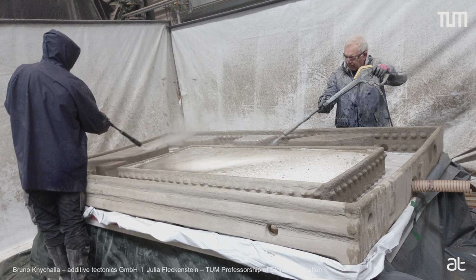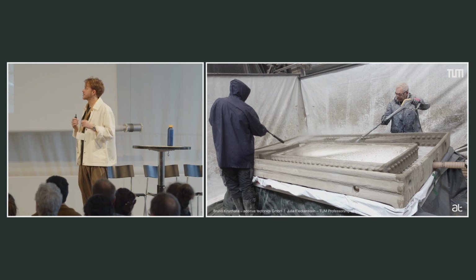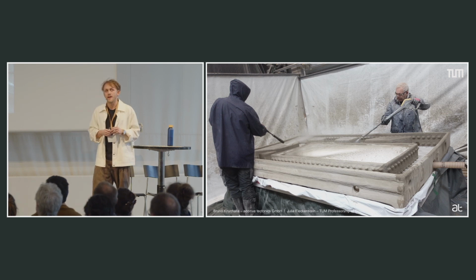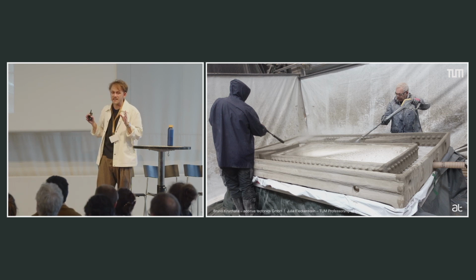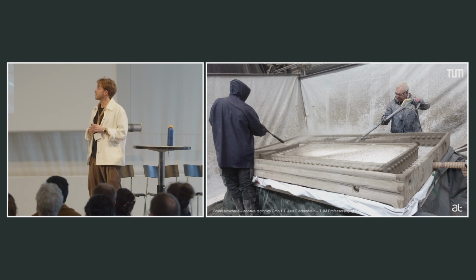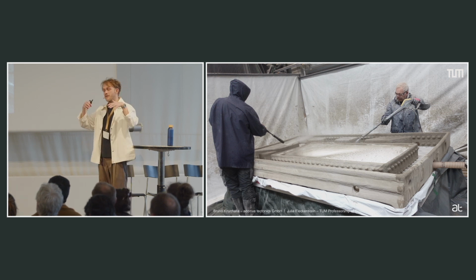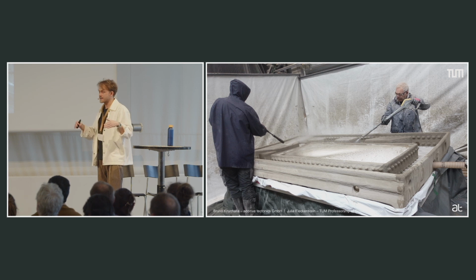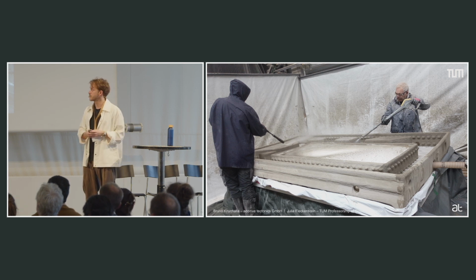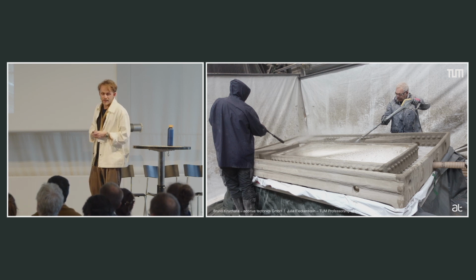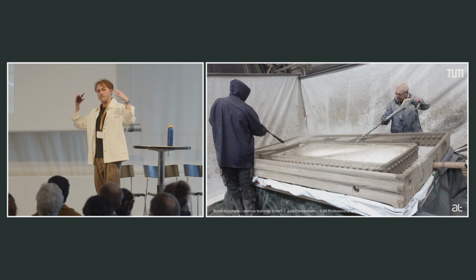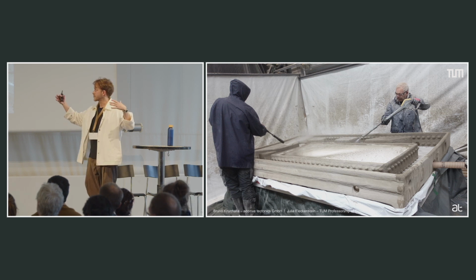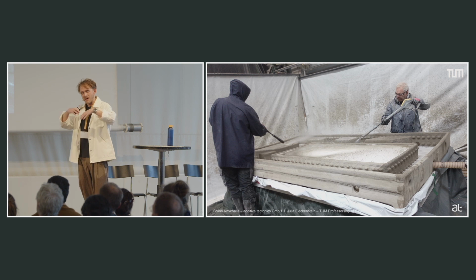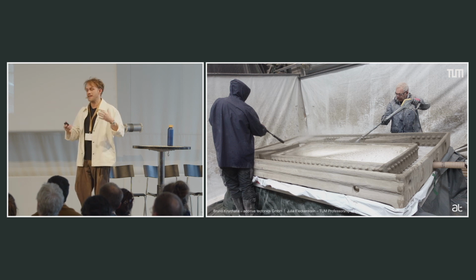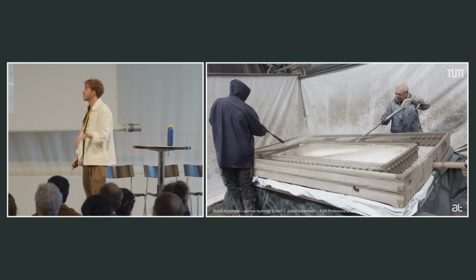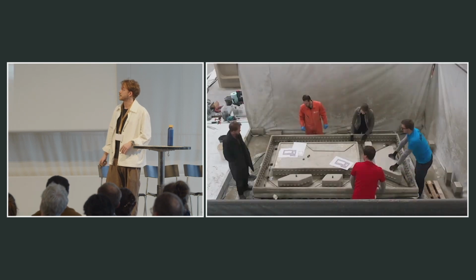Until here, we basically have an underhydrated cement. The cement is 30% underhydrated, and we need this because otherwise, when we print with full water, the water would leak through the layers, which would mean that the print would bleed. And also, if the whole part would be activated, like all of the cement, it would shrink, and the powder bed would prevent the shrinking, and then it would lead to the cracking of the part. So here we not just clean it, but also hydrate it.